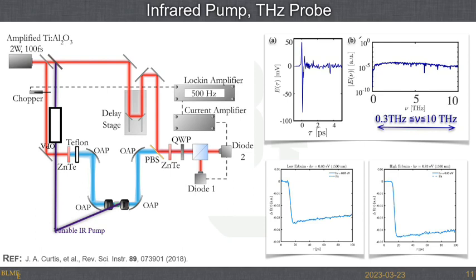I see a very fast drop in the electric field over the span of about 2 picoseconds, and then a partial recovery from all of this. What do I get out of all of this? So I created a huge number of electrons in my material, and then I'm watching them go away. And I'm watching how these materials would respond and how quickly I can shuttle electrons around in these materials.